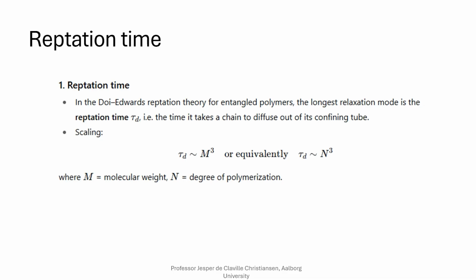The reptation time is proportional to the cube of the molecular weight. This means that if a chain breaks into two equal parts, they move 8 times faster. There's also a relationship between the data we can measure in rheometry, where we can estimate the reptation time from the zero shear viscosity divided by the plateau modulus.